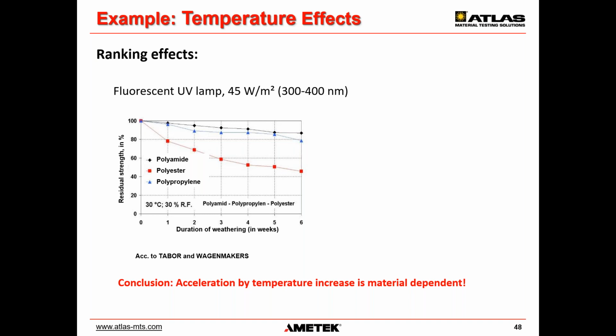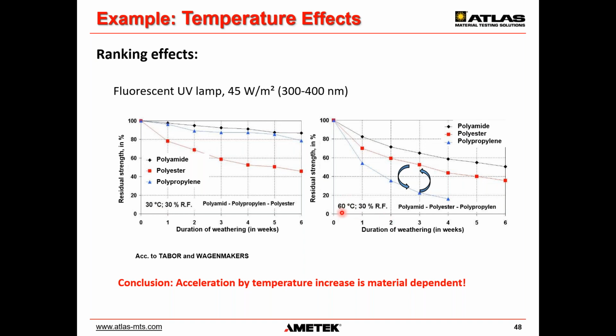Here we see the influence of temperature on degradation rates of different materials. Note in this graph that the exposure of 3 different textile fibers was conducted with fluorescent UV lamps at 30 Celsius and 30% relative humidity. And here you have the same at 60 Celsius and 30% relative humidity. You see, reversal of ranking just due to increase of temperature.